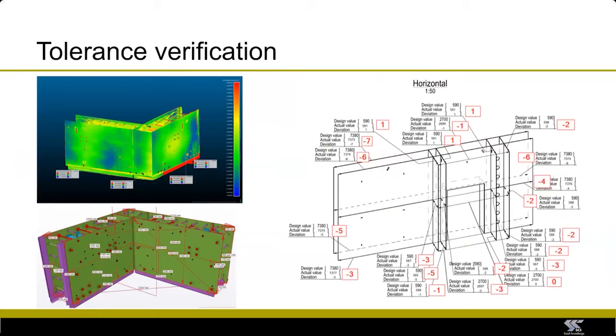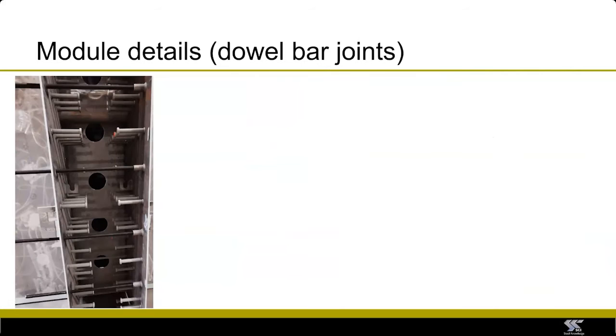The tolerances were verified in a number of ways. We had templates created for every module, which showed the tolerance requirements for each part of the module, for every tolerance that was specified, and these were checked by hand and then recorded on the template. And in addition, a number of modules were selected for laser scanning, and the results of the laser scanning were compared also with the manual measurements.